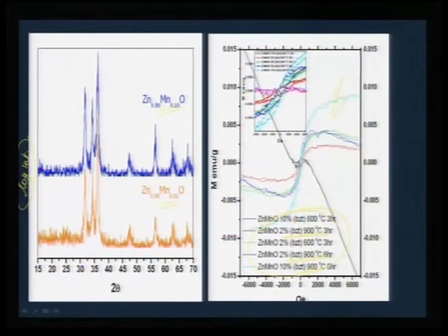It has never been reported in any of the earlier literature reports where manganese doped zinc oxide shows magnetic behavior at room temperature for any compound that is heated beyond 700 degrees. Why? Because it is an impurity which gets transformed beyond 700, and therefore only that impurity induced phase is active below 700 degrees C.